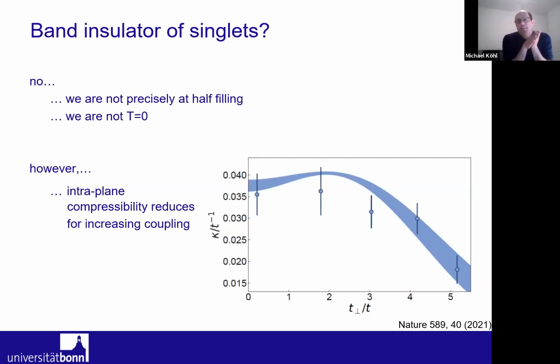However, what we have done is measure the compressibility in the plane by applying a magnetic field gradient, trying to make the atoms move and seeing how they react to this perturbation. And there we see that the intraplane compressibility actually goes down as we increase the coupling between the layers. So that is shown here. The compressibility has a certain value. The antiferromagnetic state is not precisely incompressible, firstly because we're not precisely at half filling, and also because the antiferromagnet still has some density fluctuations in order to form the superexchange interaction. So it has some residual compressibility.